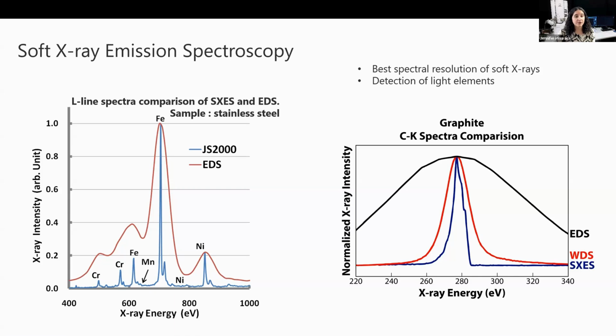Here you can see the resolution in the spectra between EDS and SXES on the left, showing an L-line spectra comparison in stainless steel. And on the right, you can see the comparison of the resolution of the carbon K emission spectra between EDS, WDS, and SXES, where SXES spectra is blue in both graphs.